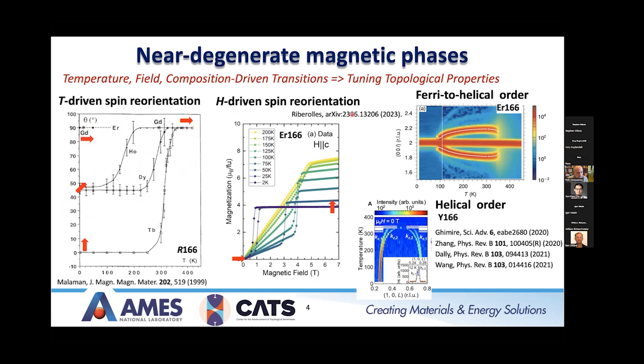So you also have these field-driven spin reorientation transitions. You can drive for H parallel to C here for the erbium. So the erbium at low temperature is in an easy plane ferrimagnetic state. You apply a field along C, you can get this metamagnetic transition, as you exit out of the ferrimagnetic state into what I'll show you later is the spiral state. You lose this step and you start getting this linear type behavior before you get this rollover to a plateau. So we have the ferrimagnetic to helical order in erbium 166, which I'll talk about before. And then of course, we also have the helical order in yttrium 166. And these are neutron diffraction patterns showing that.